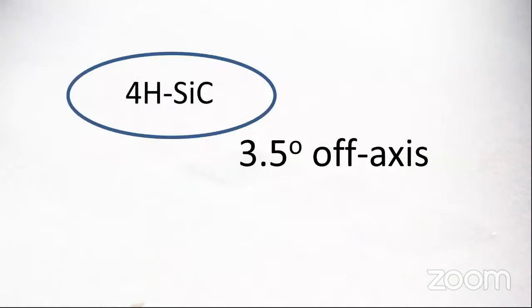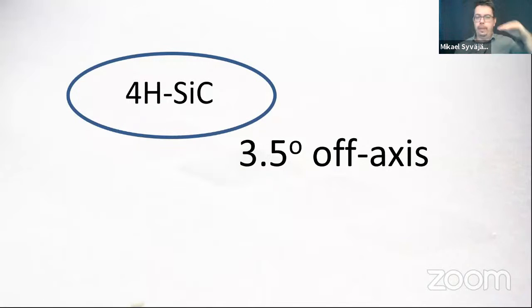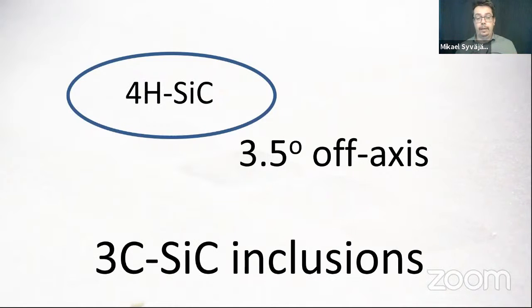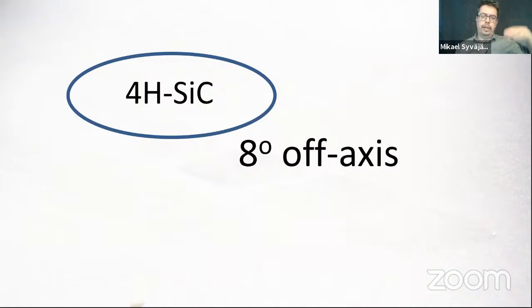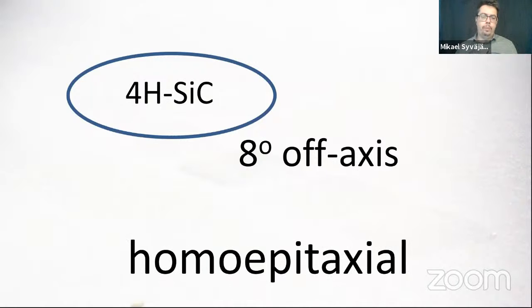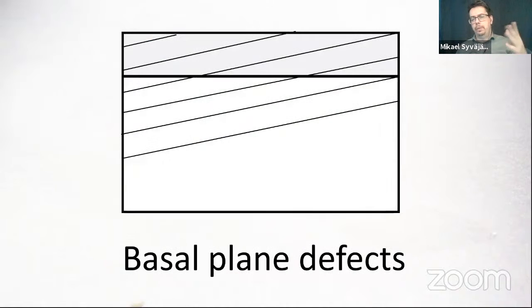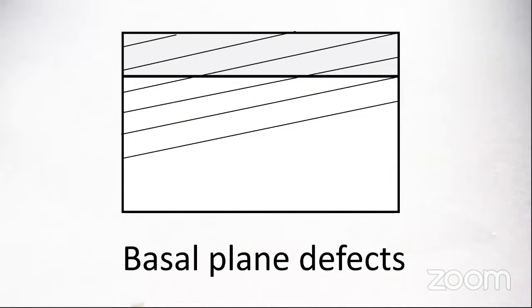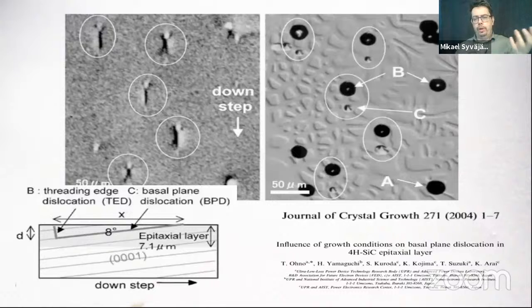And then later on, when the 4H came, they wanted to do the same trick with 3.5 degrees off-axis. But 4H is much more sensitive. So then you also had 3C inclusions in the 4H layers. So then it was changed to 8 degrees off-axis for 4H, and then you did not have the 3C inclusions. Then it became homoepitaxial layers, 4H on 4H. But the problem is that when you increase the off angle and when you have defects in plane, they will spread up to the surface and create problems. So there were other types of problems when you solved a first problem. So those emerge on the surface, and the device people will be unhappy again about these things.